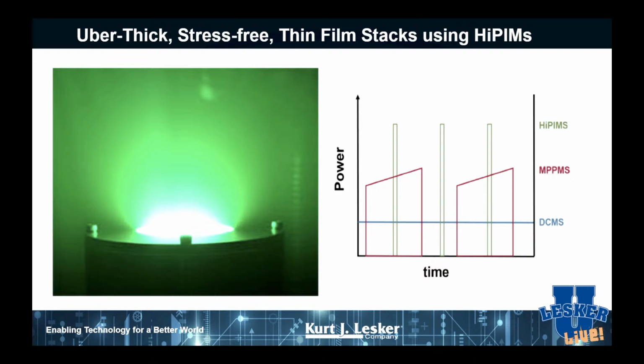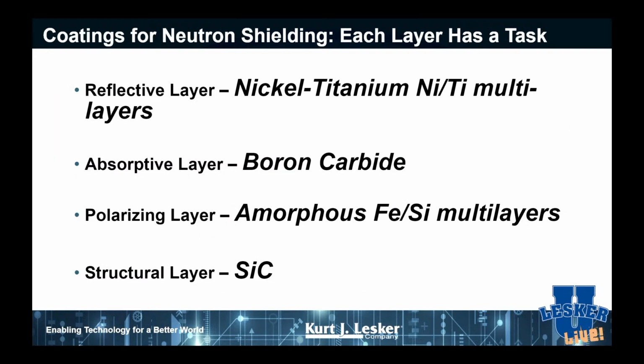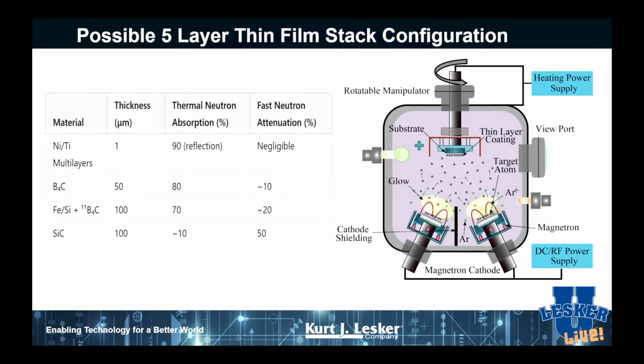Using HiPIMS, again, this is a lovely process. If you're not familiar with it, you can actually sputter with the material that you're trying to do your coating with. Again, multi-layer coatings, you can stack things up. Think about your optical coatings that you make. These things where you can do reflective layers, absorptive layers, things that polarize, structural materials.